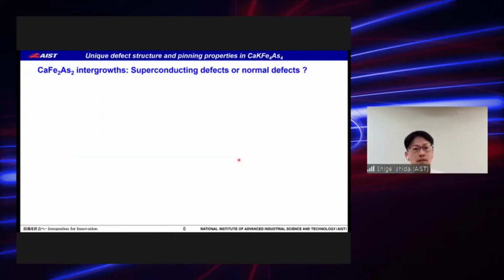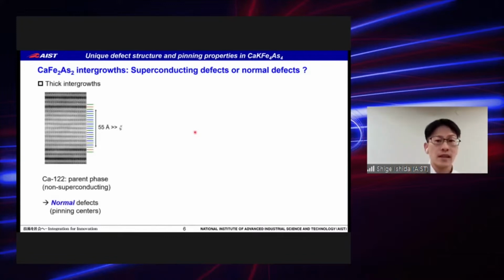So here let me discuss the nature of these defects. In the case of thick intergrowths, with thickness much longer than the coherence length of 1144, because calcium 122 is the non-superconducting parent phase, these are probably normal defects and expected to act as pinning centers.